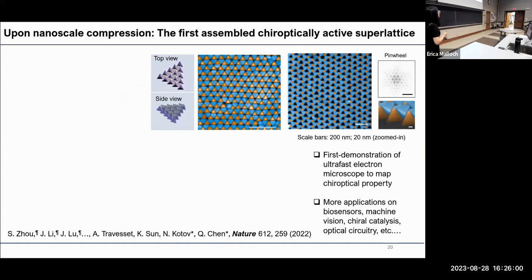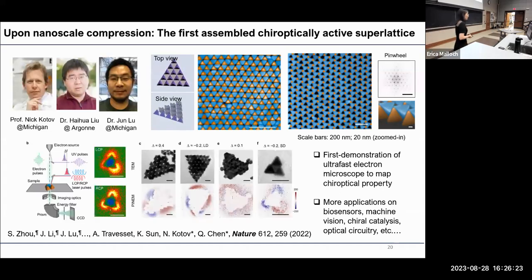Second, they're able to induce this nanoscale compression to introduce this void collapsing process. As you can see beautifully demonstrated in this video, in the end, you will have a collapsed lattice with all the triangles uniformly twisted along one direction. This means symmetry breaking, and this means chirality on the substrate. So together with our collaborators, Professor Kotov and Jun Lu at University of Michigan and Dr. Haihua Liu at Argonne National Lab, we were able to pinpoint the optical property of our self-assembled lattice.